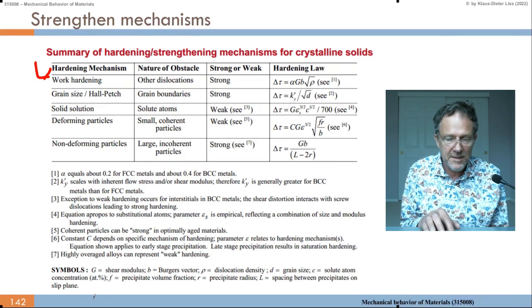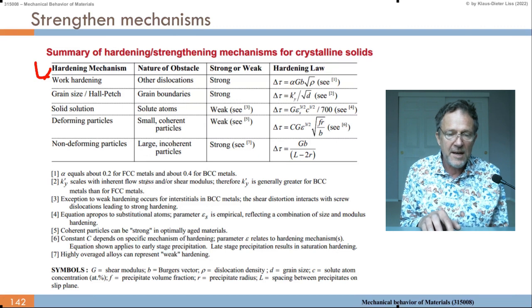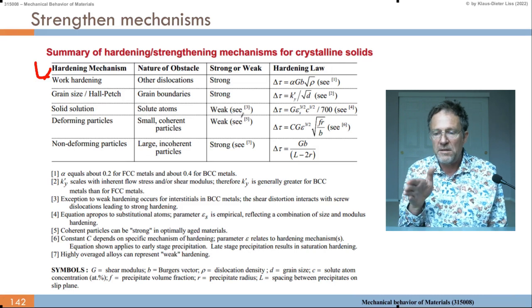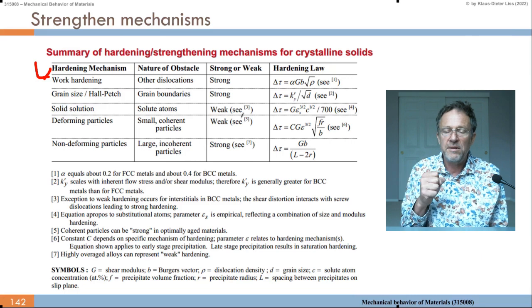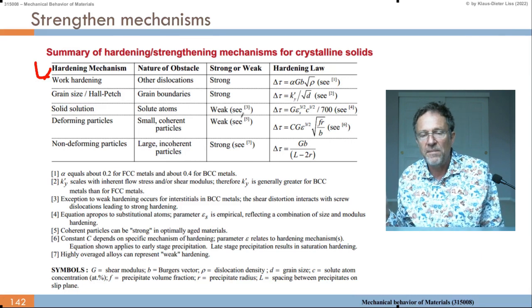So K, what is K here? It scales with the inherent flow stress and/or shear modulus, therefore K prime Y is generally greater for BCC metals than for FCC metals. So this is a scaling factor which we may consider. Then solid solution strengthening. The obstacles are just the solute atoms distributed over the crystal lattice. And that's relatively weak. I said already, if there's one point defect, the dislocation can move it. It feels a little bit.